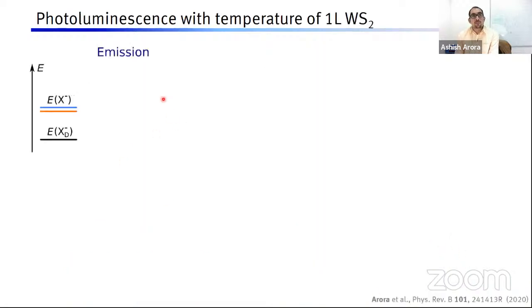So what we do is we study the photoluminescence with temperature. Earlier, we studied absorption with temperature on monolayer tungsten disulfide. Let's suppose there are two types of bright trions, and let's suppose there is a dark trion state slightly below these bright trions in energy. Then the population of trions in such a system will have a Fermi-Dirac redistribution, because a trion is a fermion. Most of the trions at low temperatures will occupy the dark state, and the bright states will emit very little light.